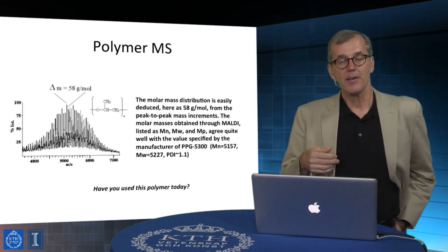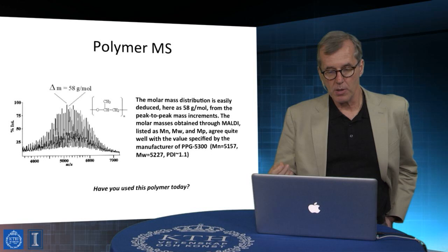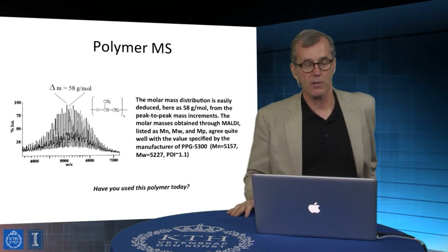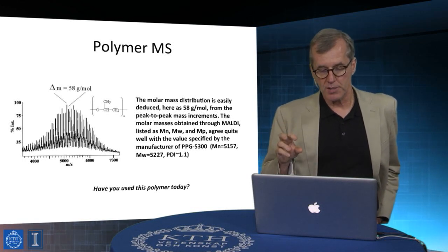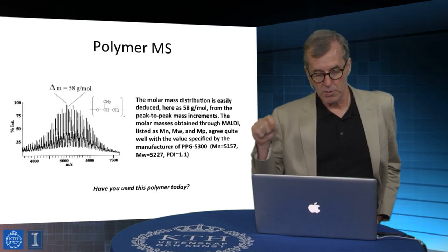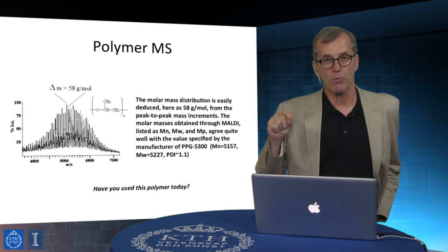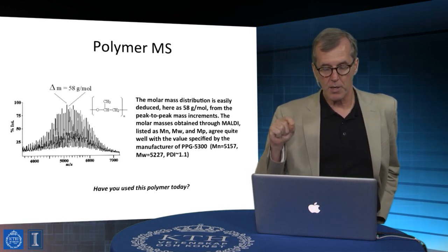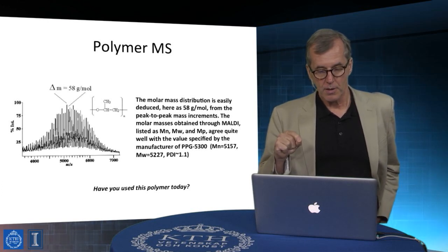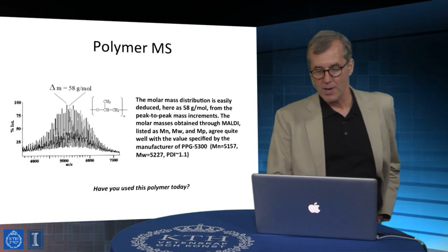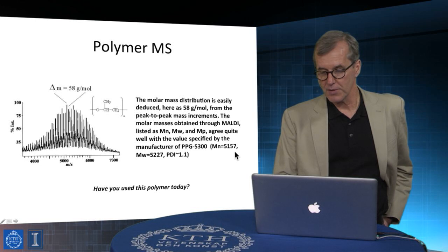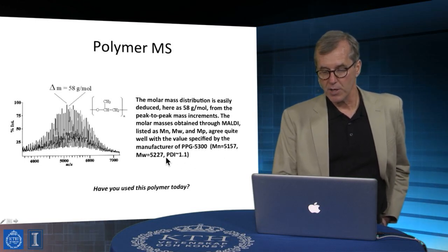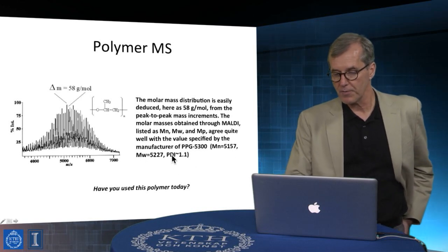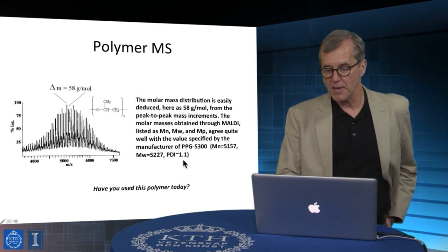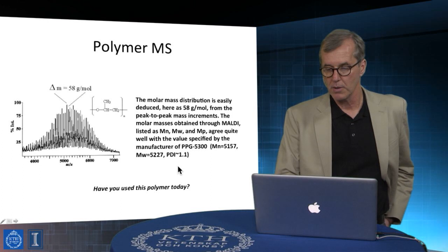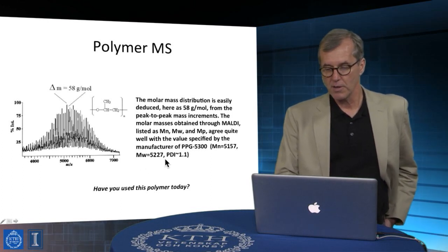Now, this is a technique that's capable of really fantastically high resolution, and I mean fantastically high resolution in the sense of a large operating dynamic range, so you can measure really large masses with very high precision as to what their actual mass is. Okay, and so I show here an example of a sample that has a number average and weight average molecular weight of 5157 and 5227, polydispersity index of 1.1. So this is a really monodispersed sample of really high order, a profoundly good sample.